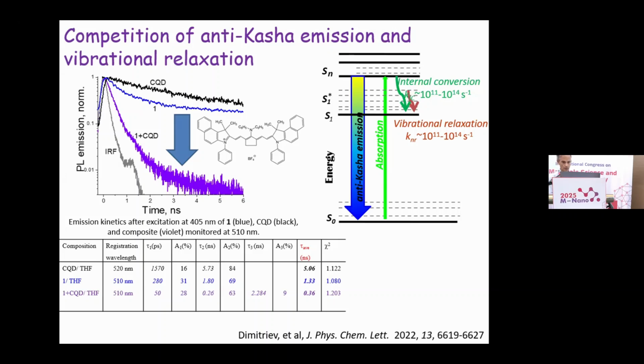First, as I told you, the relaxation of the excited electron from the S2 to the S1 energy level is very fast, because the processes of internal conversion and vibrational relaxation are of the order of 10 to the minus 11 to 10 to the minus 14 seconds. So in order to realize Anti-Kasha emission, the rate of this transition should also be very high in order to compete with these processes.